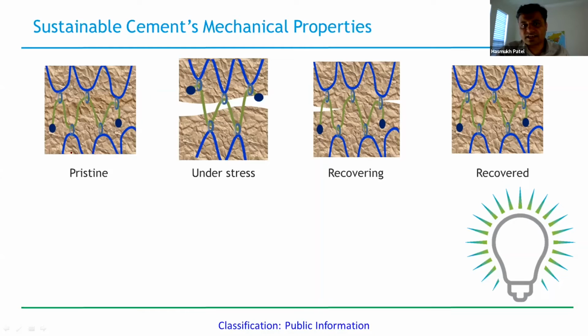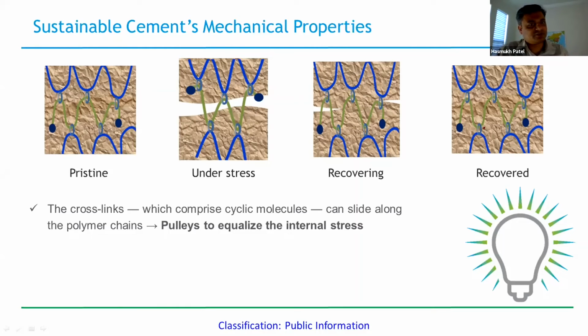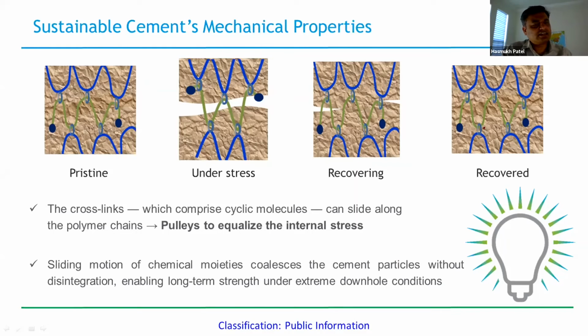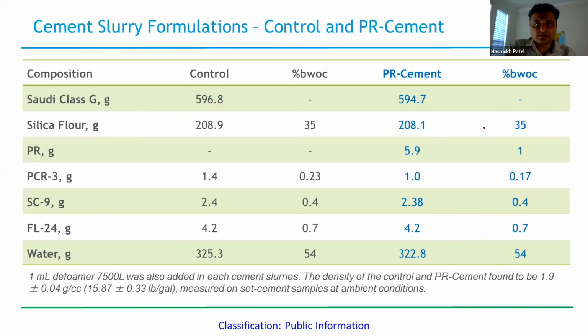But even if there are cracks, what will happen? Because there is a repulsion between the cyclodextrin rings, it can actually recover and heal the cement particle. So basically the cross-links, which comprise cyclic molecules, equalize the stresses because of pulley effects and the sliding motions of the molecular moieties, which allows the cement particles to coalesce and not disintegrate from the structure.